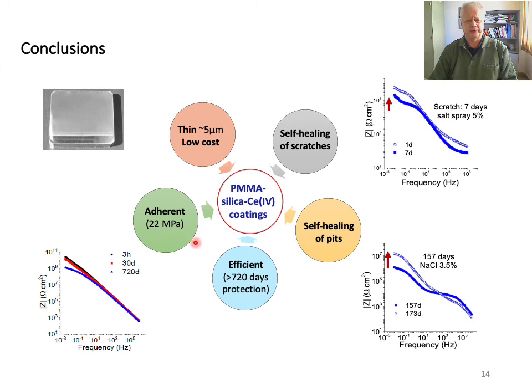Now, in summary, the structural and electrochemical investigation performed in this work showed that PMMA silica cerium-4 coatings with a thickness of only 5 micrometers have a very strong adhesion to the aluminum substrate and provide excellent and durable corrosion protection. This physical barrier is not only efficient, with more than 720 days of immersion in standard saline solution, but also smart, providing active corrosion protection by self-healing of pits and larger artificial defects exposed to aggressive environments.